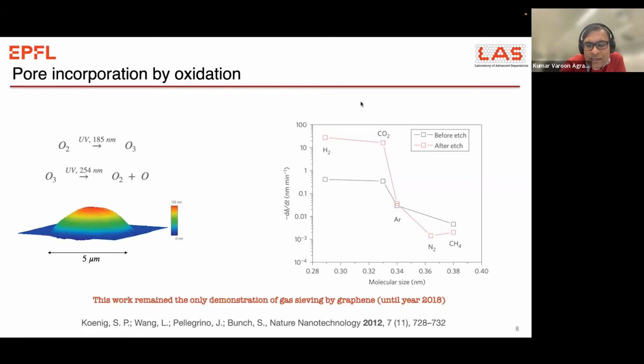You can read the molecular size on the x-axis. On the y-axis is the leak rate of these molecules, much faster than the bigger molecules like nitrogen and methane. So this was the proof of principle. This was from my 5 micron size pores, but this proof of principle stayed until 2018, because at that time, nobody could actually make devices of atom thick membranes without any cracks or tears. And it was also very difficult to reproduce these chemistry experiments.